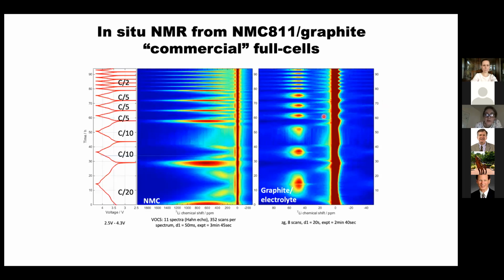now Katerina's work where she makes full cells. So instead of cycling the 811 against lithium, we now put graphite into the mixture. And so this is the spectrum of the NMC, and it's this broad signal. You pull the lithium out and it disappears. And at the same time, you can see now this signature here coming in and out. And that's the lithium going into the graphite. So you can watch the various staging compounds, and this is the signal of lithium in the stage 2 and the stage 1. And so you can track that all together in an operando cell.